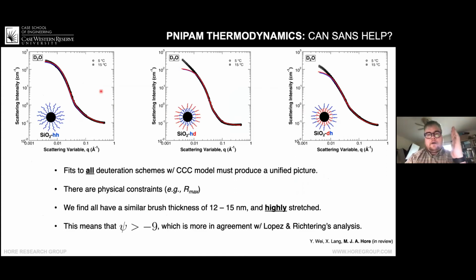And if we fit all 3 of these deuteration schemes, we have to arrive at the same result. Assuming that the deuteration doesn't impact the interaction, then all of these different deuteration conditions are looking at different pieces of the polymer chain. So we have to get a single unified picture. There are also constraints here. The polymer chain can be stretched, but it can't be stretched longer than its maximum extension, R max, which is about 20 nanometers. And what we find when we analyze it is the brush thicknesses are about 12 to 15 nanometers, and they're highly stretched.